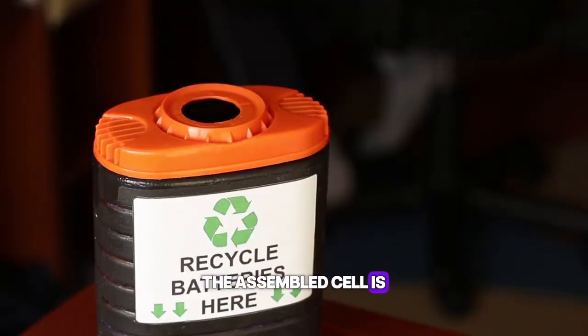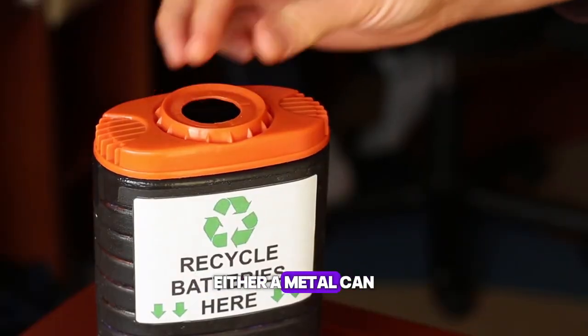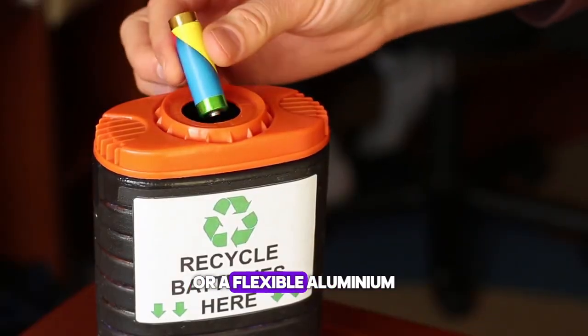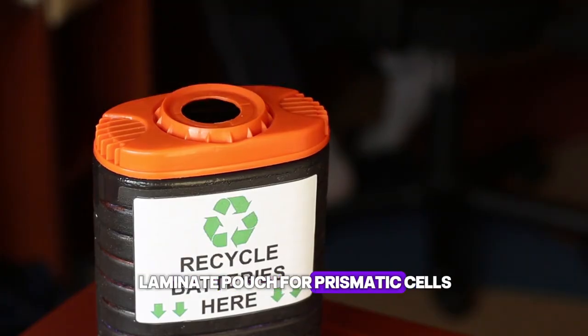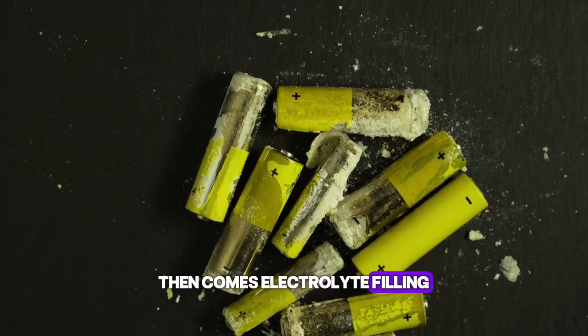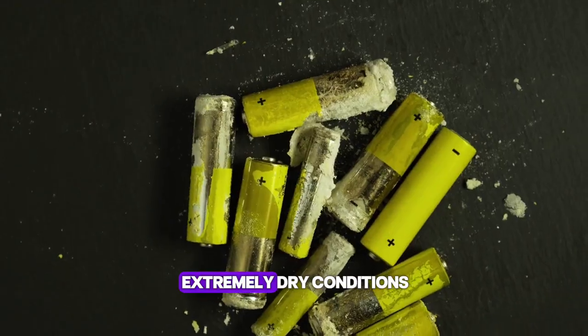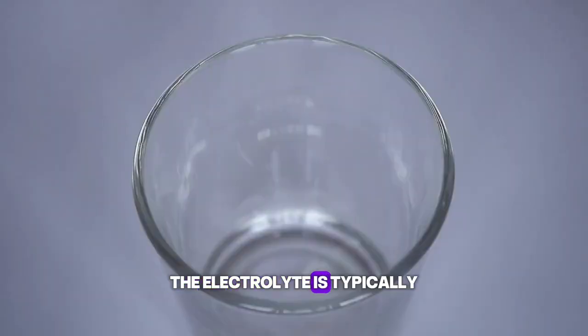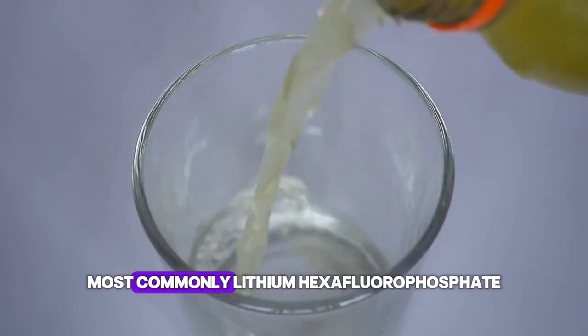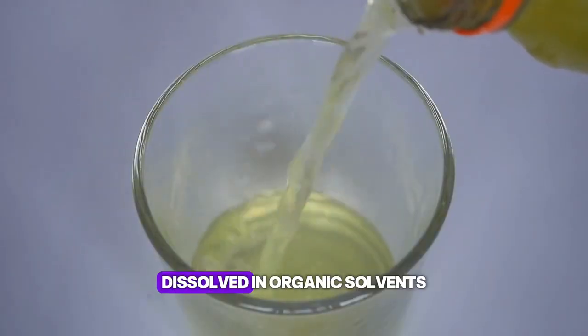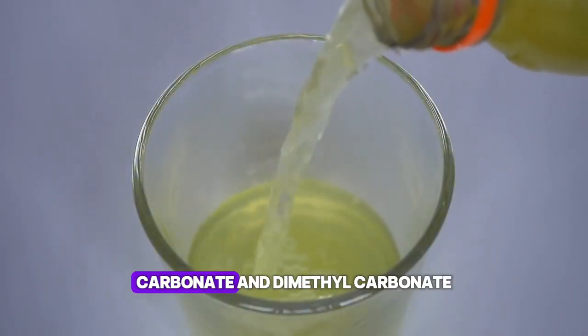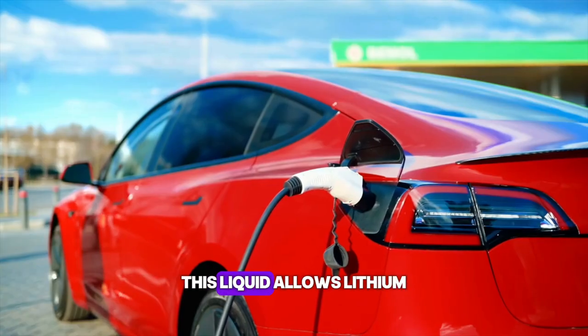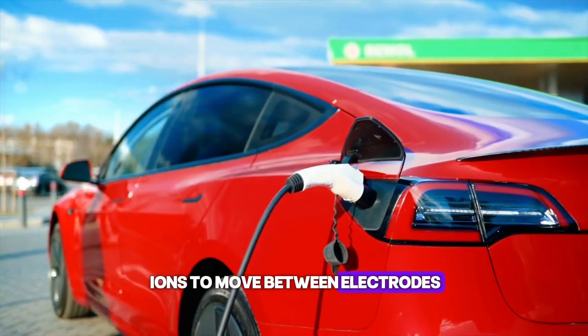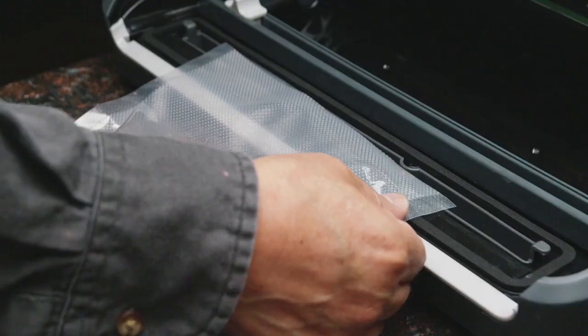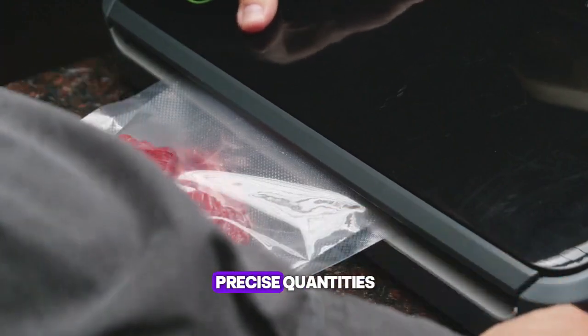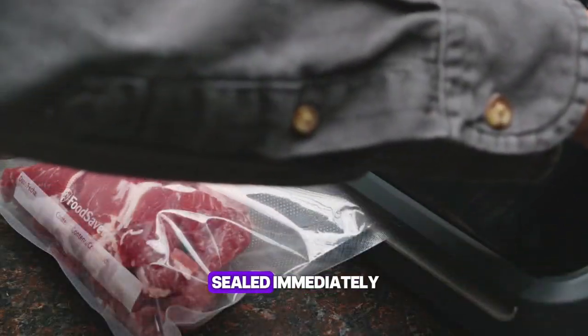The assembled cell is placed in its container, either a metal can for cylindrical cells or a flexible aluminum laminate pouch for prismatic cells. Then comes electrolyte filling, a process conducted in extremely dry conditions. The electrolyte is typically a lithium salt, most commonly lithium hexafluorophosphate, dissolved in organic solvents like ethylene carbonate and dimethyl carbonate. This liquid allows lithium ions to move between electrodes during charging and discharging. The electrolyte is injected into the cell in precise quantities, and the cell is sealed immediately.